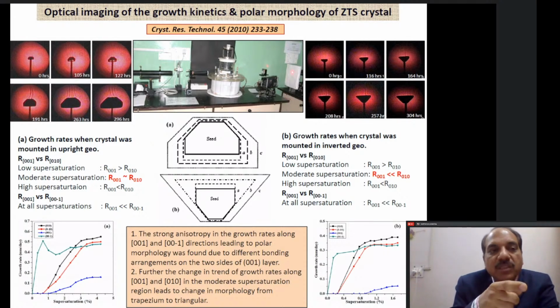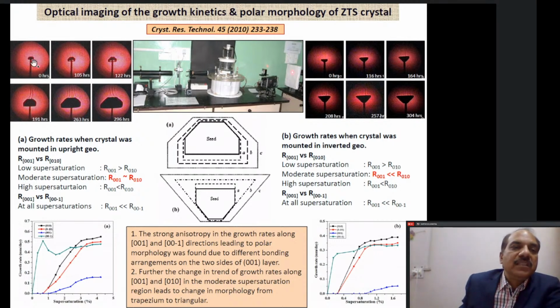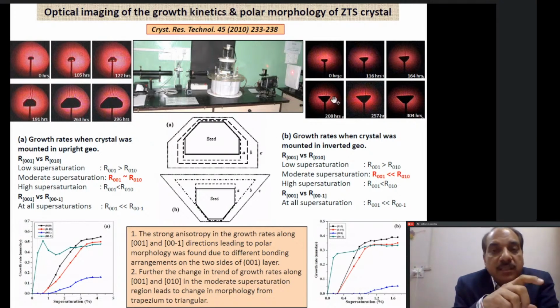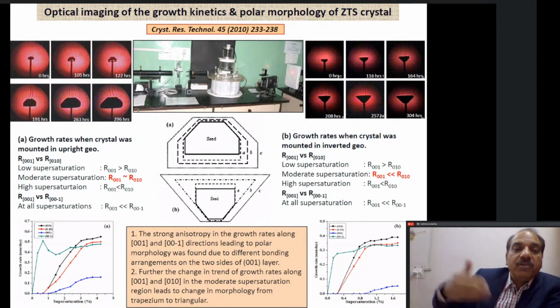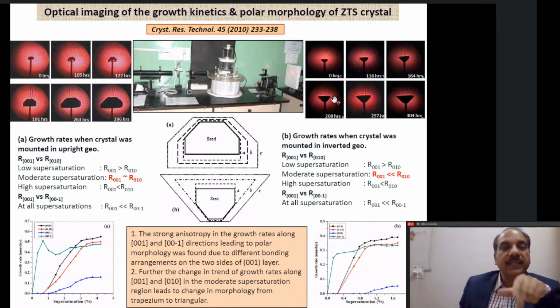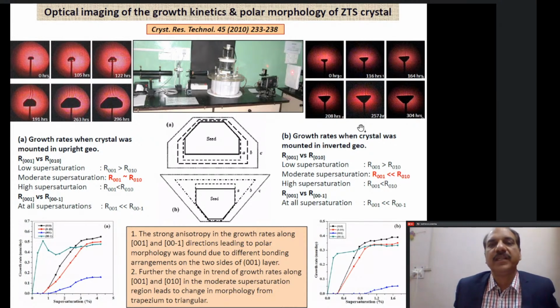And you will see that this crystal is growing. On the left hand side, if you see these images, this is the glass rod on which this crystal is growing, right? And basically a half-cut hexagon type of thing is the crystal which is growing, and these times which you see, 0 hour, 105 hours, 122 hours, 191 hours, are the duration of the experiment. So you can see that this experiment continued for more than 10-15 days, continuously. This is the video camera which I was talking about, a Sony Handycam which was continuously recording this experiment, and we used to record these cassettes, and then run these cassettes on our PC and take out these images at corresponding hours, right?